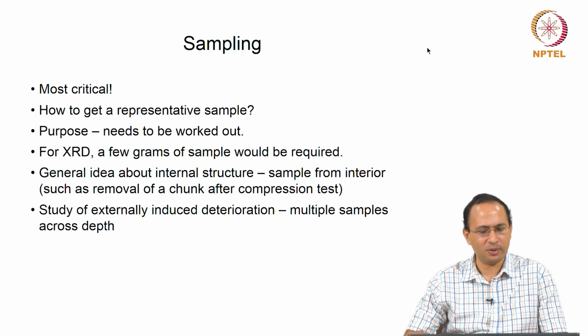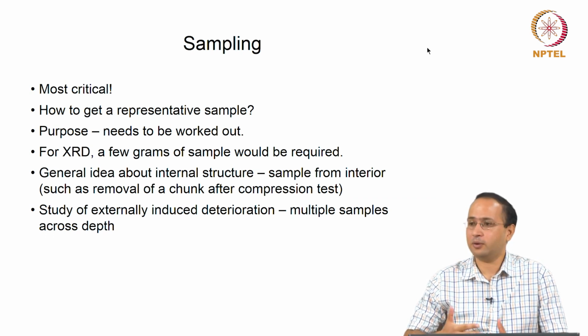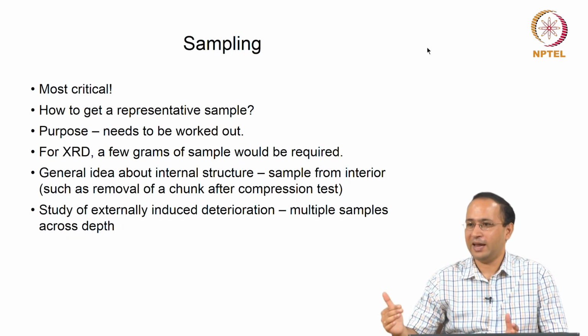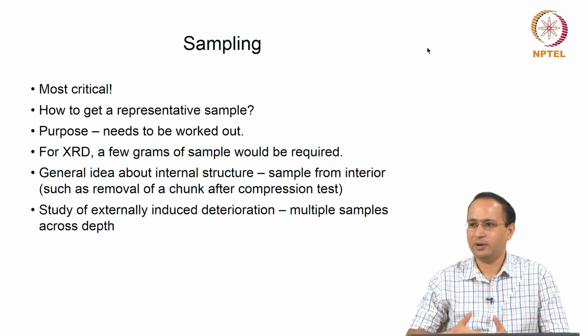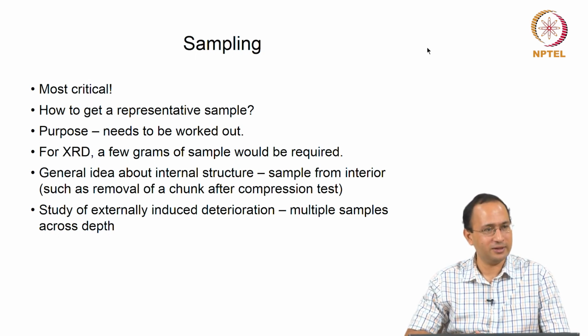So these are the things you have to keep in mind, and if you are looking at externally induced deterioration, it could be any type of attack like salt attack, sulfate attack, right. Now it is important to get multiple samples across the depth, because you are exposing your sample, or maybe in real life your structure is exposed, and characteristics across the section will depend on the extent of diffusion of that aggressive salt or solution, right. So you need to have samples across the depth. So these are a few basic things you have to keep in mind.